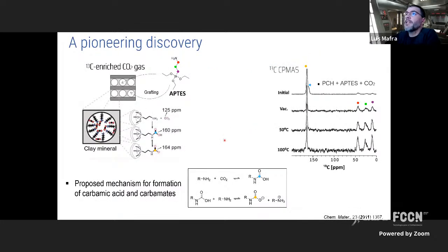Our endeavor into this realm of CO2 capture mechanisms started in 2011. We published a paper in Chemistry of Materials where we proposed for the first time a different reaction path, different from the one I showed you previously. We could identify a third entity, another molecule, which is called carbamic acid here, okay, which was thought impossible to form on solid surfaces. This was identified in solutions by liquid NMR, but because of its high instability, it's hard to isolate on solid surfaces. However, you could see a peak here, okay, at room temperature. You could see this peak labeled in blue that with just 5 minutes of vacuum is gone. So it's very unstable. And this was previously assigned to urea, okay? But urea is very stable, and it doesn't go away easily with 5 minutes of vacuum.